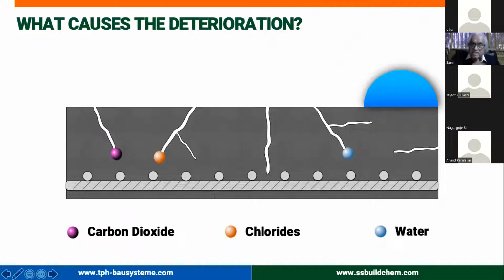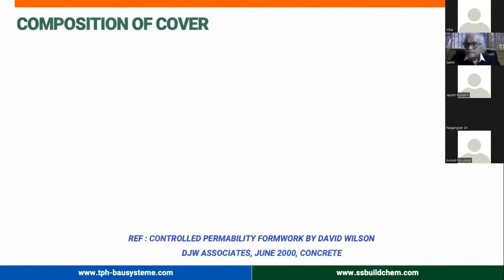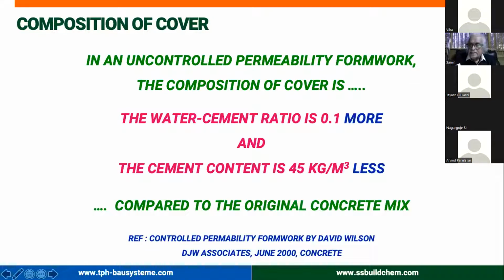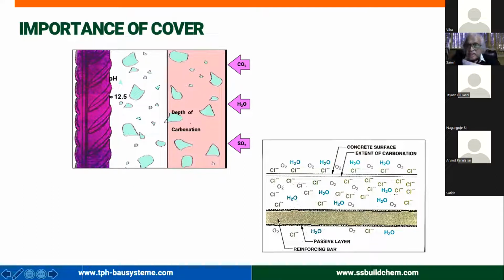A very simple thing: it's the carbon dioxide, chlorides and the water that create corrosion. Basically, concrete is a basic system. The whole protection to concrete comes from its cover. That's the whole concept. This is so simple. But in reality, in our country or any other place, the concrete cover, which is supposed to be one of the best parts of the structure, since it is directly in contact with the environment, is one of the worst parts. It is having 0.1 water cement ratio more, and it is having 45 kg per cubic meter less cement. So this is how the concrete cover starts getting breached through carbonation or chlorides.